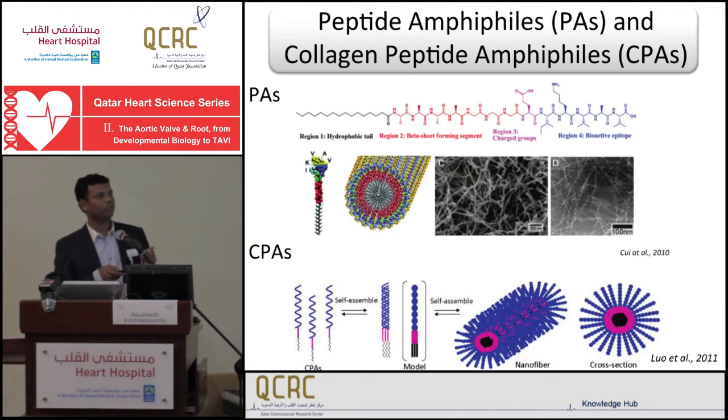But I would like to introduce first what is peptide amphiphile, what is the difference between the normal collagen and this peptide amphiphile nanofibers. You can see that the basic unit of the peptide amphiphile is the hydrophobic and hydrophilic. This hydrophilic, not only the hydrophilic, the charged or signal residues, the signaling epitopes can be introduced here. You can see the same structure is reproduced here. This is the hydrophobic and this is the signaling part. So when they arrange together, because of this hydrophobicity, they can form clear, long nanotube structures, and the epitopes are exposed on the surface of the nanotubes.